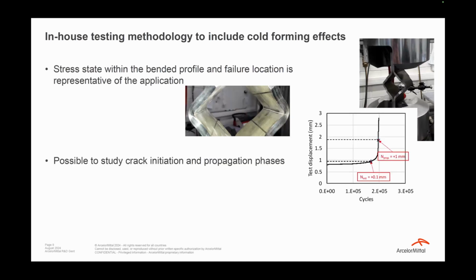Once you do the test, what we are doing is that we check the test displacement. And with checking this, it's possible to study the initiation and the propagation cycles. So you will see that as the cycles go by, there's a certain limit after which your stiffness loss will ramp up and ramp up. So we have a practical limit of 0.1 millimeter where we say that, okay, at this point, we have a crack initiated. And then if the displacement has increased to 1 millimeter, we say that the crack has propagated enough. So that's how we come up with the initiation and propagation cycles once we make the test runs.